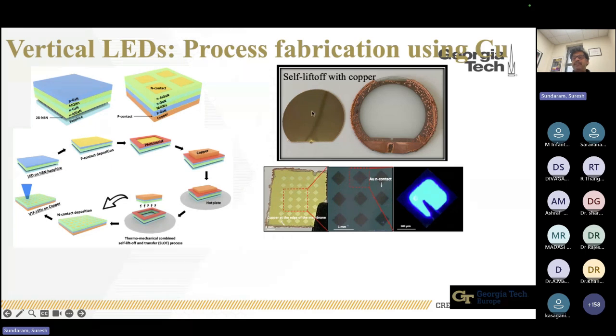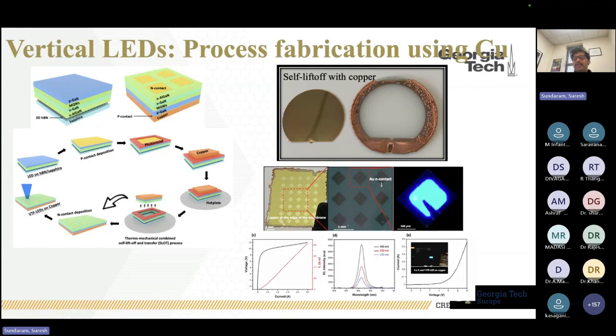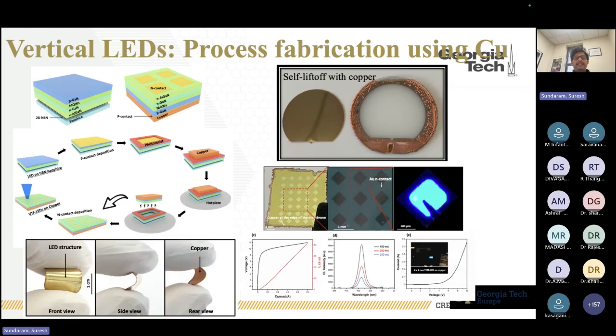So these are after self lift off, and then we have individual devices or device arrays on top of these layers. We flip it and then we put N-type metal contact on top of it to get blue light from it. So these are the IV and emission characteristics of these devices. You can see that it is really flexible without any issues. There are no cracks, or mechanically there is no failure of devices when we are using these devices. That is realized by these processes.